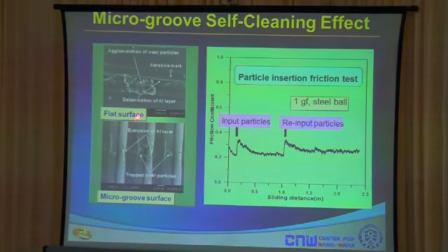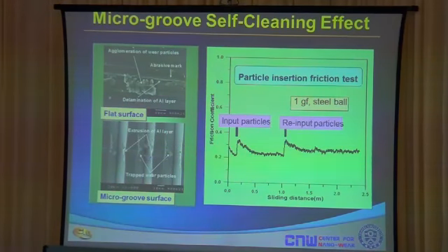The way to do that is by texturing the surface so that the textures are able to trap the wear particles. And these are undulated surfaces that we've been researching over a long time now. And this is an example of such a surface. What you're looking at here is a silicon surface with grooves artificially fabricated on the surface to trap the wear debris that is being created. On the top surface, you see a regular flat surface after the wear test. What you're looking at here is, in the case of the bottom surface where you have micro grooves, it is able to lower the friction by trapping the wear particles in these grooves.